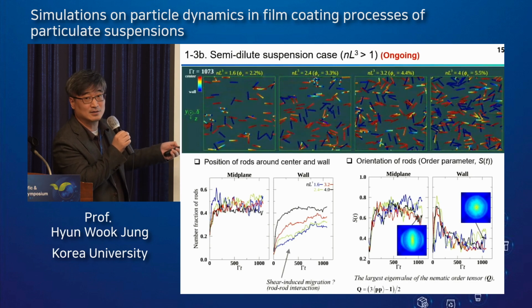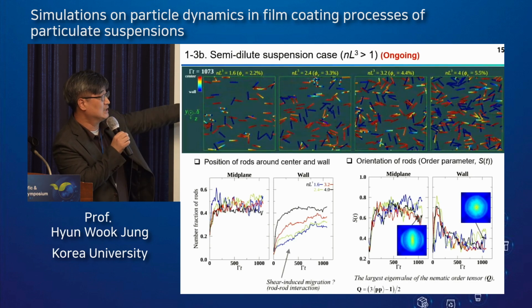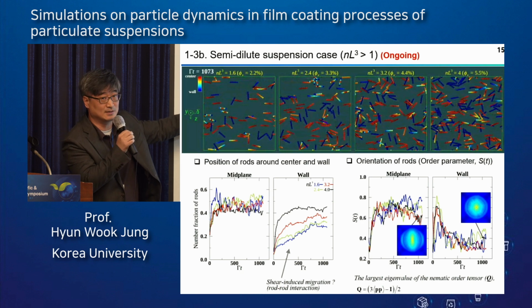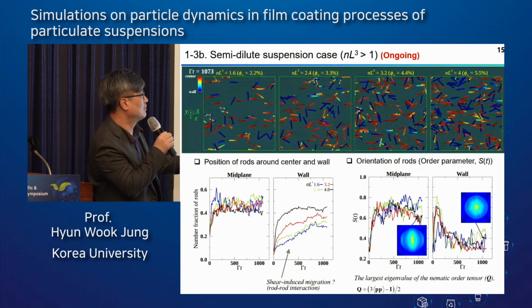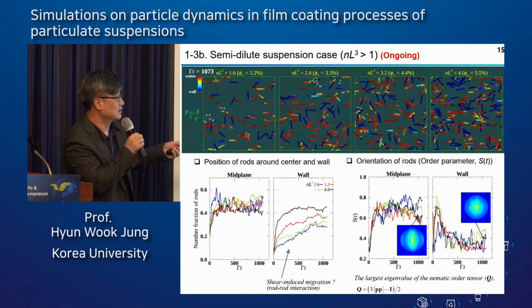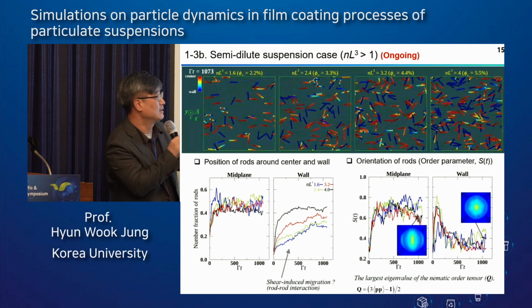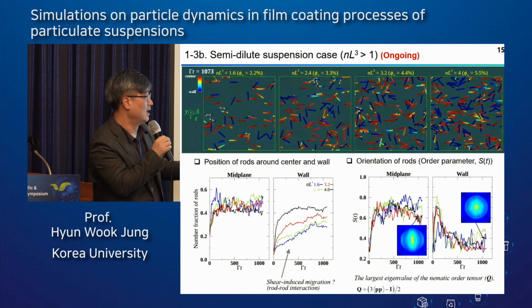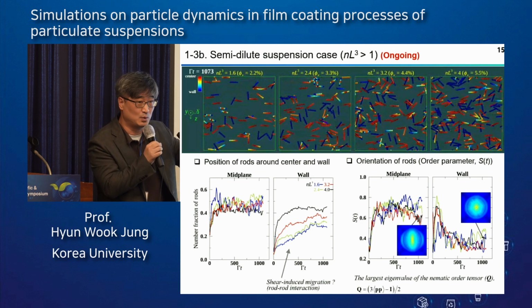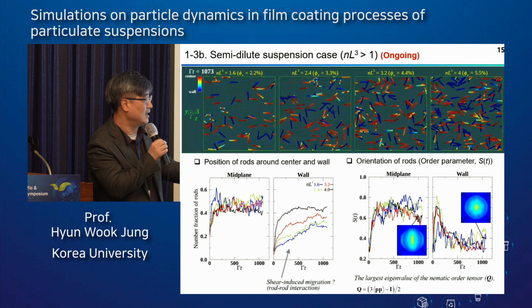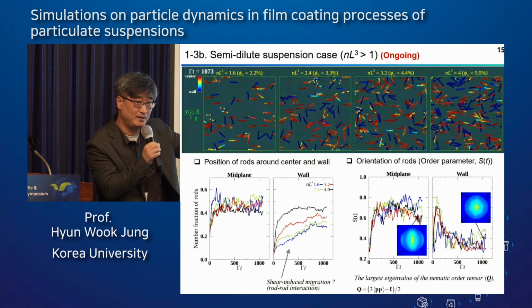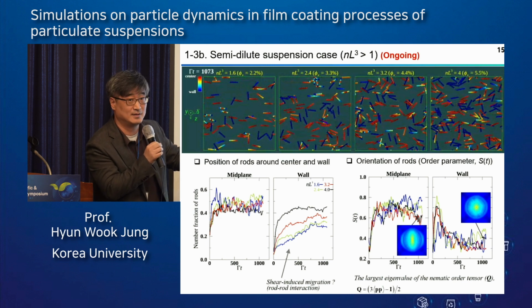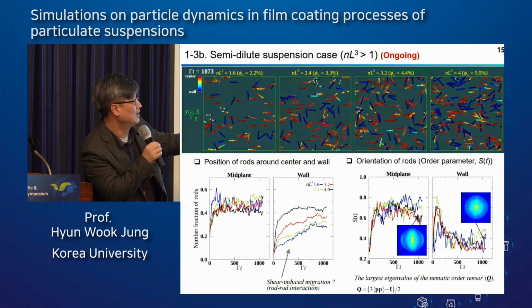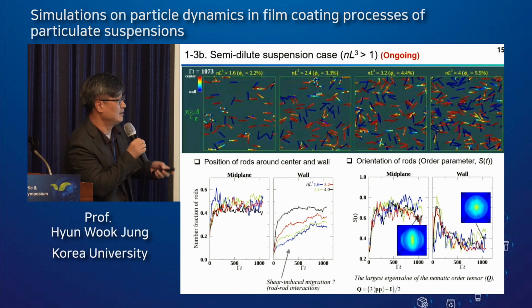However, the number of rods in the middle plane stays constant regardless of concentration. Also, considering the orientation of the rods, colloidal rods moving near the wall are randomly distributed, and colloidal rods moving in the mid-plane are very highly aligned, as shown here. You can see the orientational differences between the two colloidal rods.